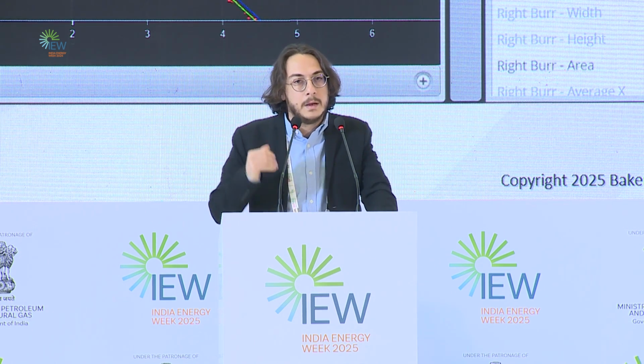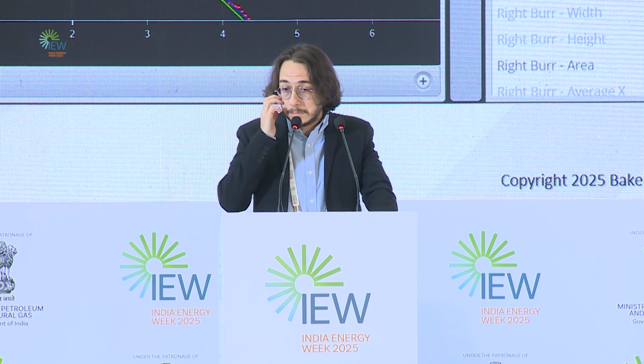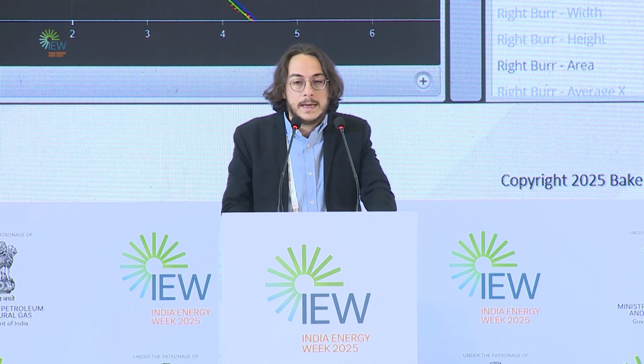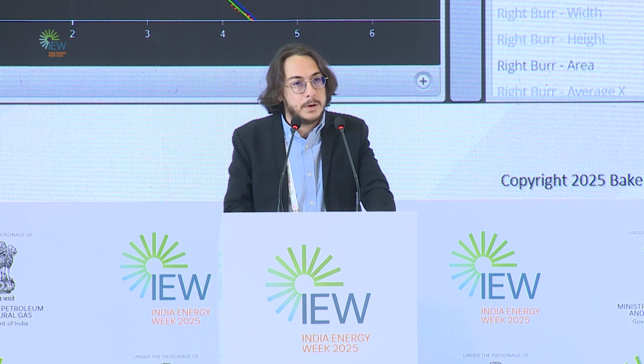Then, once we have this information, we can use that to quantify the burr. So we take our edge point, we take our lines, and we state that all the points that are above the lines in a certain area close to the edge point are basically burrs. So with this information, we can analyze this burr from a geometrical standpoint and understand its height, its width, and the integral beneath it, its area.